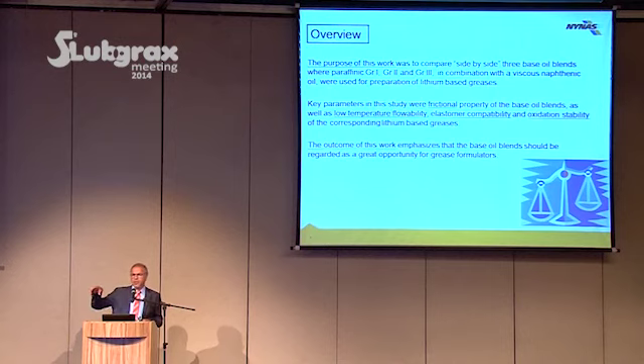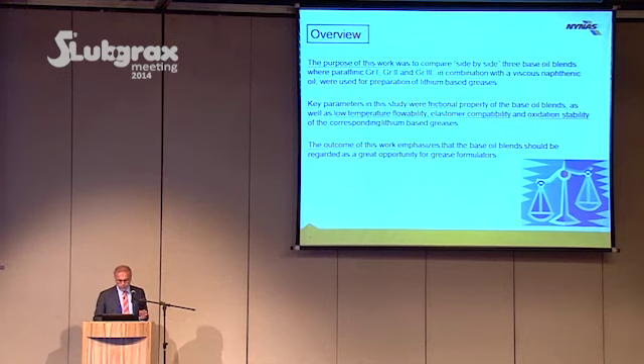For CV joint grease, it is important that the grease or lubricant which you use has to be compatible with a certain type of rubber. Very often it is nitrile butadiene rubber or chloroprene. In this study, we use chloroprene. So we made lithium greases based on those 3 oils. So the outcome is, in fact, as I mentioned already, that it's a great opportunity for the grease makers to upgrade their current formulations just by blending.